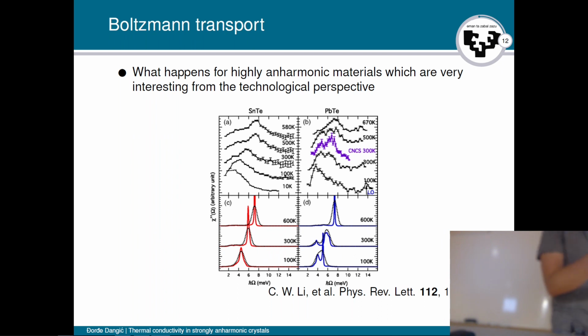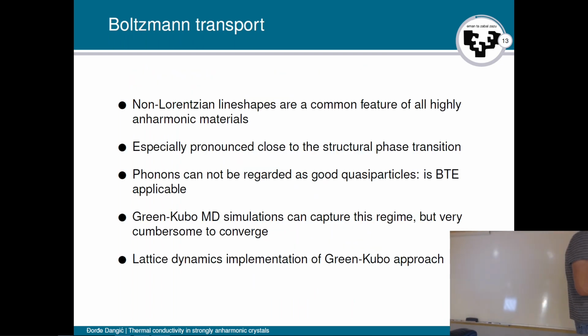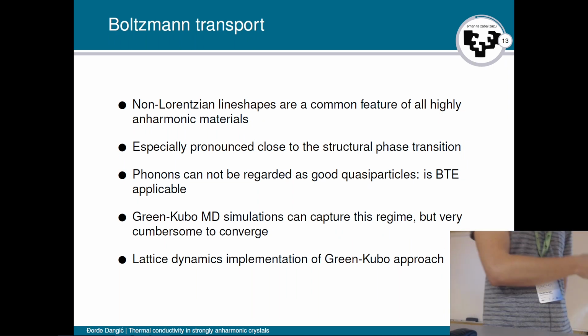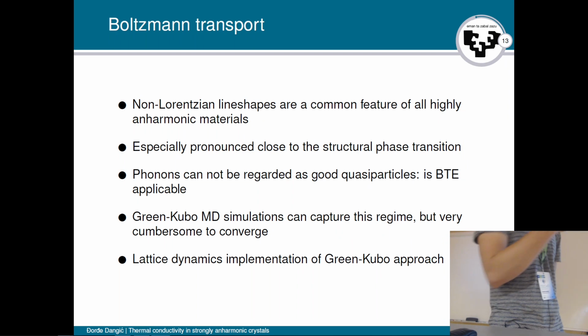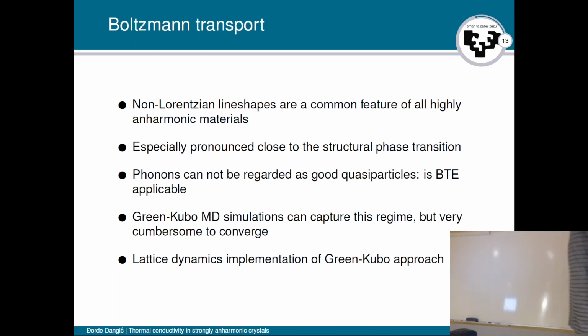So, as you increase the temperature, you would assume it becomes more anharmonic, but when you increase the temperature, it also goes away from the phase transition, so it becomes more harmonic. So, yeah, it is kind of a weird trade-off situation. The anharmonicity is especially pronounced close to structural phase transitions. And because it has these double peaks and does not have Lorentzian line shapes, it cannot be regarded as good quasi-particles, meaning they do not have well-defined phonon lifetimes, nor well-defined phonon frequencies or population numbers.